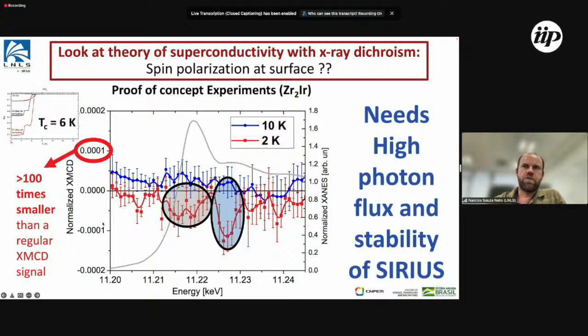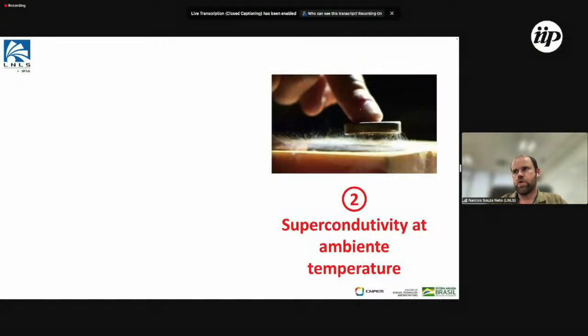The difficulty of this is that this signal is about 100 times smaller than what we would normally measure for a magnetic material. So nobody is actually prepared to do these experiments in the world. We are trying to do the first, to probe this and open a new area of studies of superconductivity to validate some theories. And we hope that with the high photon flux that we have at Sirius and all the improvements, we can do this well. But let's come back. What about superconductivity at ambient temperature?